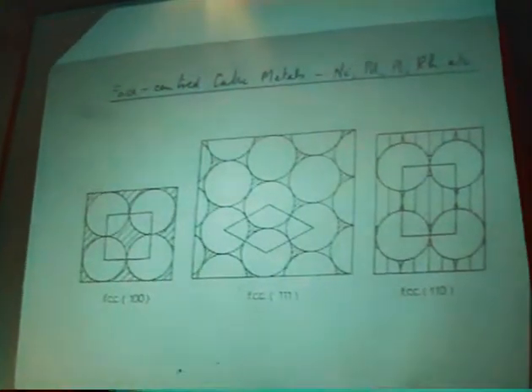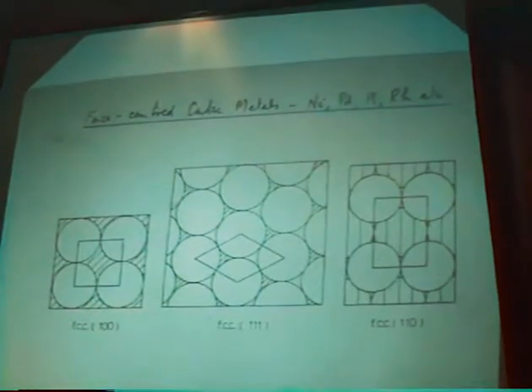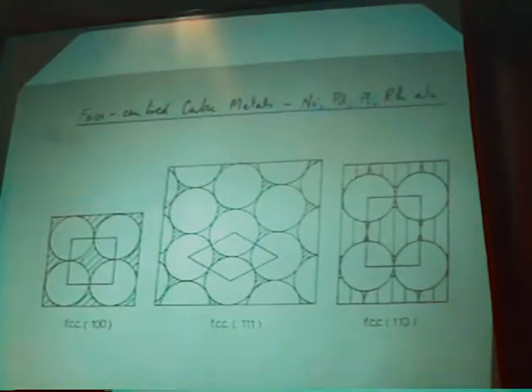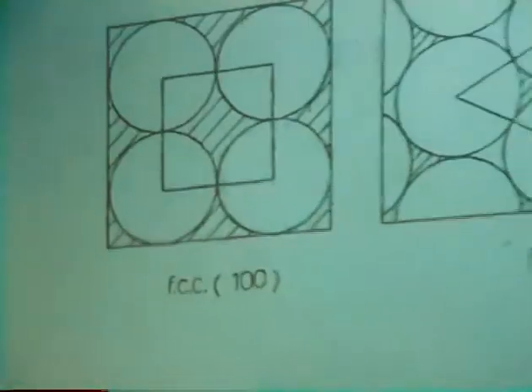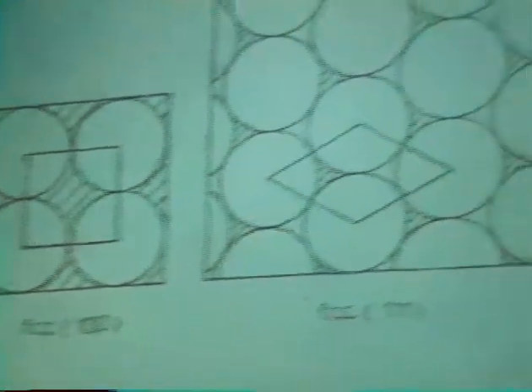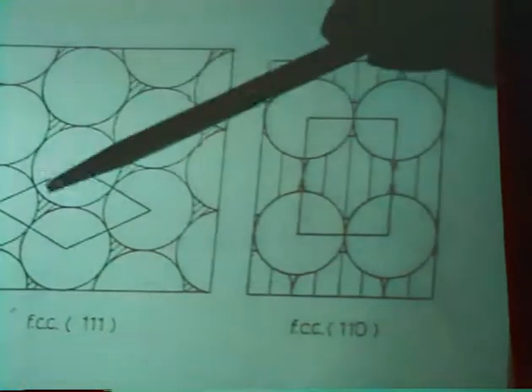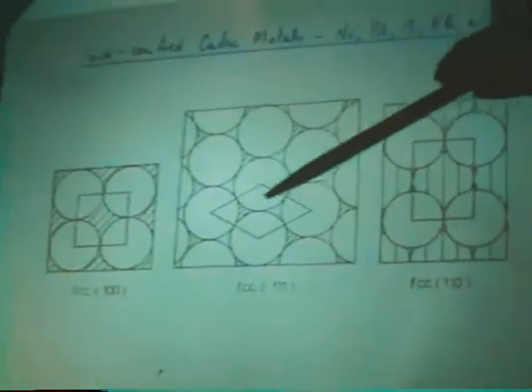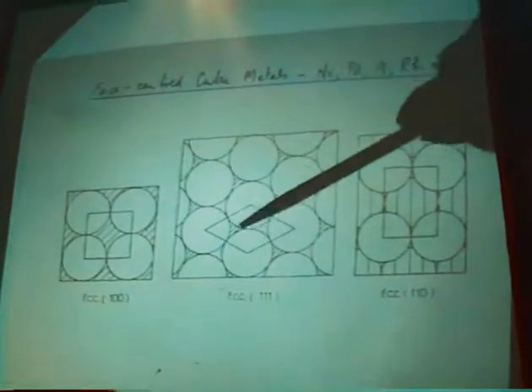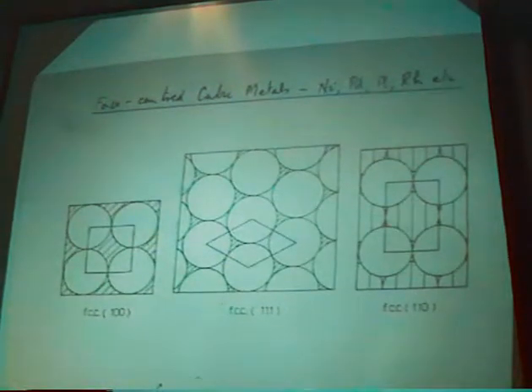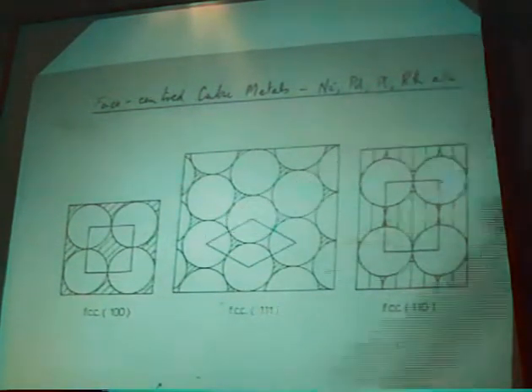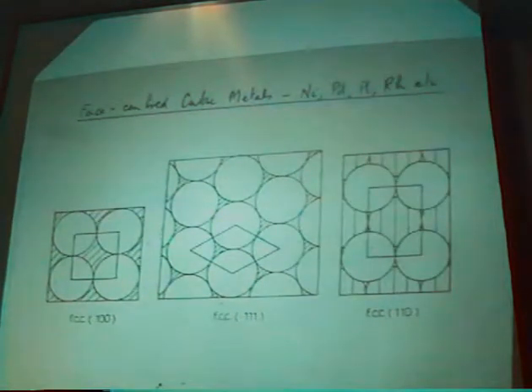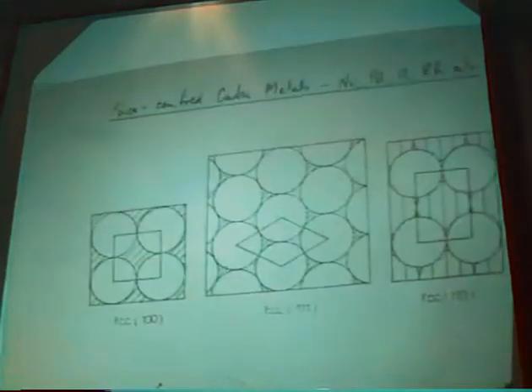For a face-centered cubic metal, those are the arrangements of the metal atoms. Of course, even within a unit mesh of any one of those, there could be different species. The close-packed one could give threefold species, in fact two slightly different threefold species, depending on whether there's another metal atom in the next layer or not, or linear species or twofold bridge species. But at least now one is moving to a simplified system where one can be more confident about vibrational assignments.